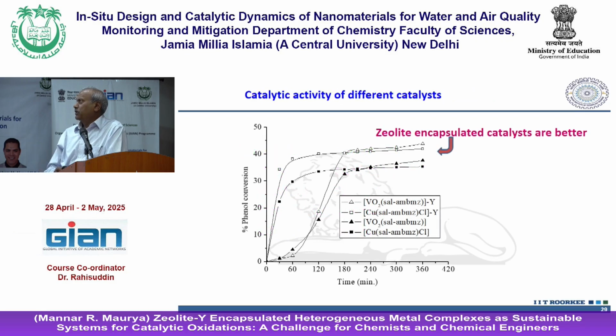And look at here. When you compare the zeolite encapsulated complex with the simple metal complex, the zeolite encapsulated one is giving the best result. Though a little bit more time is required, but it's okay. The catalytic activity is really better. But in terms of really good results, it's not, because conversion is going to a maximum of 40 to 45% in any case. But it's better. Some results are coming.